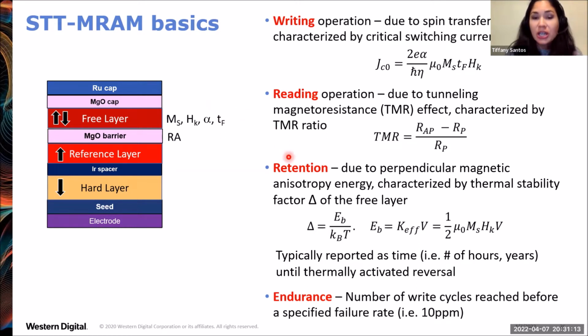The reading operation is done by the tunnel magnetoresistance effect. The retention, so this is how long can the free layer retain the magnetization of the written state, either up or down, before you get a thermally activated reversal, and then your memory would be lost. So the retention comes from the perpendicular magnetic anisotropy energy, and that's characterized by the thermal stability factor delta here. And retention for products is typically reported as a unit of time, for example, a number of hours or years before you get a thermally activated reversal.